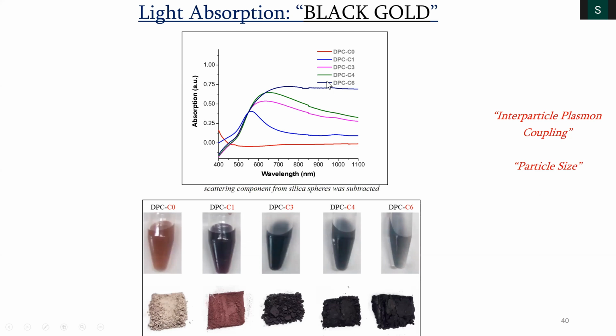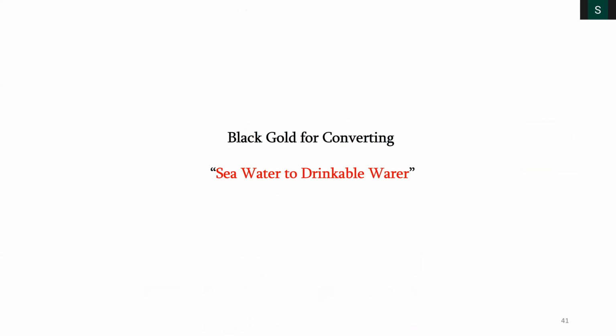So what is the advantage? It's not just because of the color, but that black color is because it absorbs all the light, and then that light energy gets damped to produce heat, thermal heat, or the hot electrons. And that thermal heat can be used for catalysis.